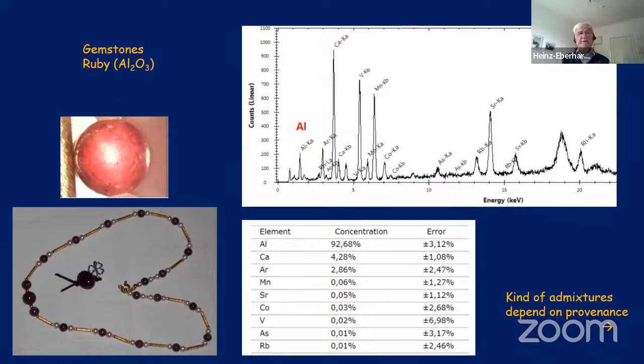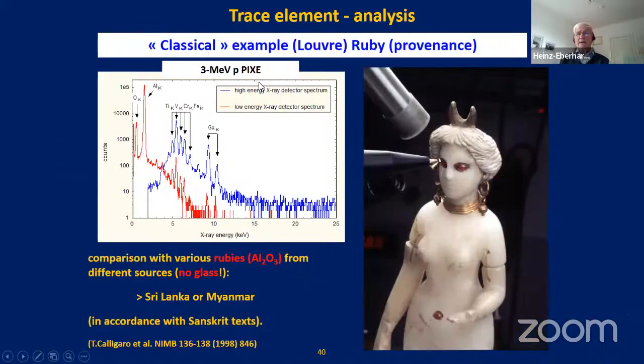Many years ago, by a different technique, people at the Louvre were looking at rubies used as inserts for the eye and for the belly button of an alabaster figurine. And they figured out it was not done by the photo effect using an X-ray photon coming in, but a proton coming in, kicking out the electron. My colleagues at the Louvre laboratory, the C2RMF, found a nice contribution of gallium impurities in these gemstones. And that could be identified to rubies originating from the region of Sri Lanka or Myanmar. So the impurity tells you about the provenance of the gemstone or the minerals found.